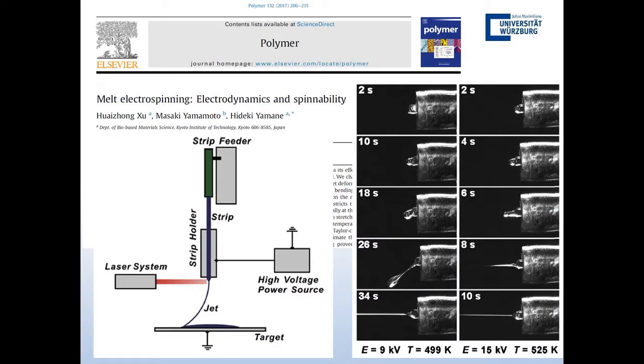this is a recent work done with a laser. Again, within 10 seconds you can establish a nice jet. And here you have a cold filament, and this is hot now, and this is cool down. And this may allow us to work with polymers as difficult as polyglycolic acid, which degrades normally after 2 weeks in the body, and thermally degrades very, very quickly. We've tried to melt electrospin it, it's a mess. Probably even worse a mess than that old picture that I showed you.